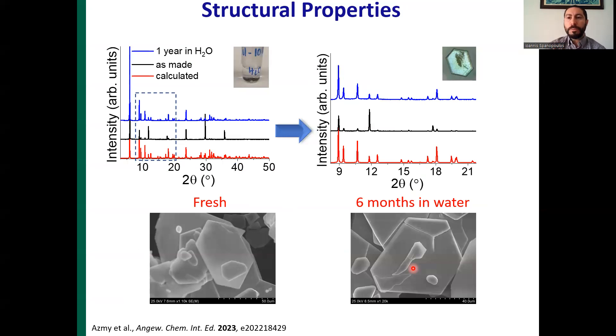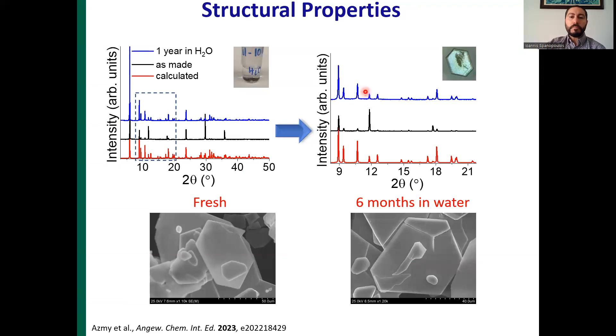The corresponding material is water stable for over a year. Comparing the calculated PXRD patterns of the fresh material and after one year immersed in liquid water, there is no loss of crystallinity. SEM imaging of the crystal surface also confirms that after six months in water, there is no surface degradation.